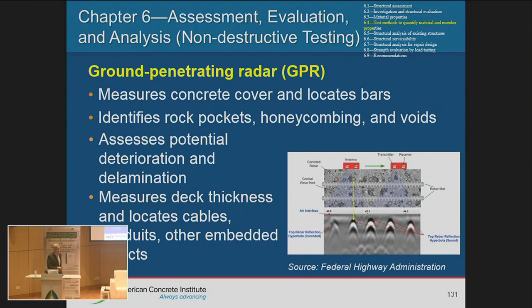GPR is very widely used, and the results are usually accurate. I've used that equipment on many of my projects. The one that I mentioned earlier, where the owner had put a lot of cabinets around the slab, around the column, were initiating punching shear. We used this equipment, and we found out that they had other issues too: the slab was post-tensioned.